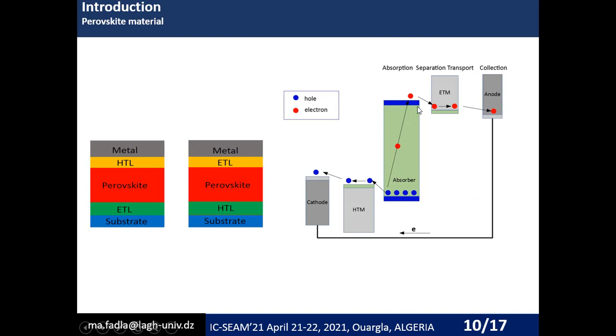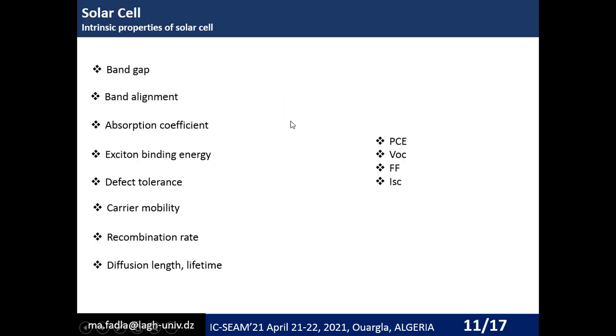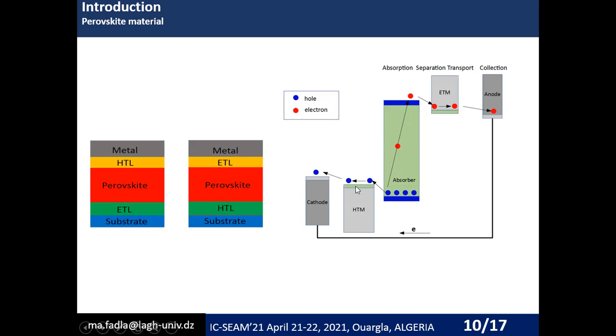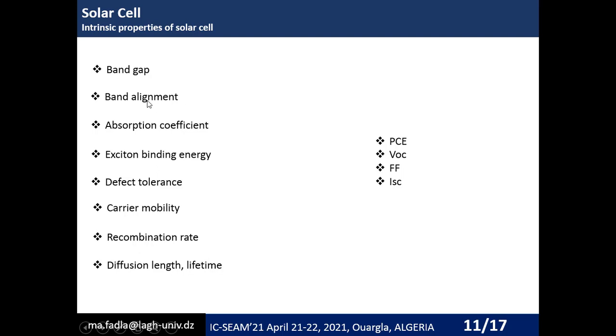So in my work I only focus on the absorber material, which is the perovskite. What can we do using the ab initio method? We can calculate the band gap, and we can do the band alignment by calculating the valence band maximum. For the absorber, the maximum of the valence band and the minimum of the conduction band should be aligned with the hole transport material and the electron transport material. That is what we call the band alignment. For this process, it is really necessary to choose a suitable partner for our absorber.